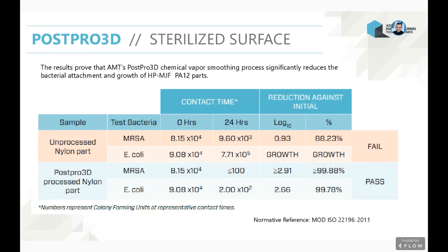As far as skin contact, we also have done the third-party analysis to prove that. The results that I'm presenting here are specific for nylon 12 from multi-jet fusion, but if your polymer has the ability to pass skin contact applications, PostPro3D and the chemistries that we're using are not going to fail your product. They are also going to pass the test. And this is also a very significant observation and significant result that is unique to PostPro3D.